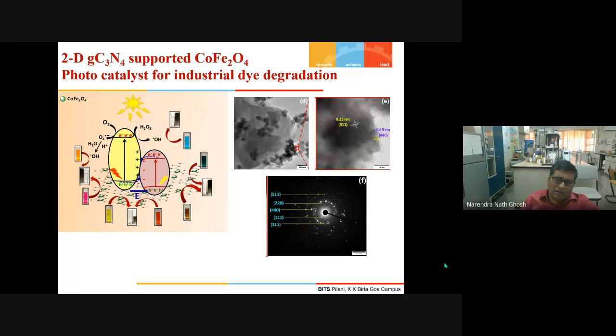Now, what we have targeted is that we have first prepared the graphitic carbon nitride supported cobalt ferrite nanoparticle. Here you can see that the TEM shows that some of the nanoparticles are on the surface of the graphitic carbon nitride and some are inserted within the layers of graphitic carbon nitride.